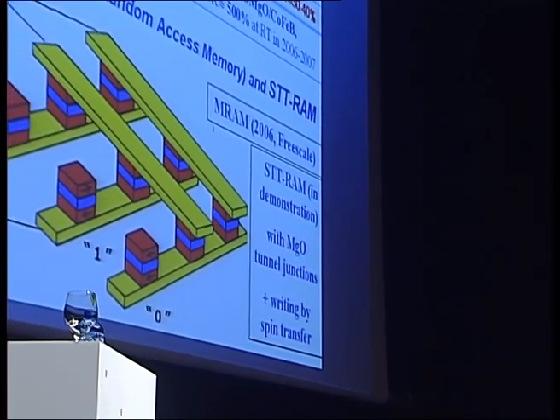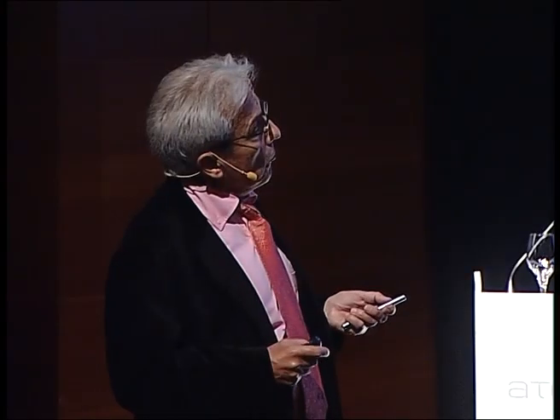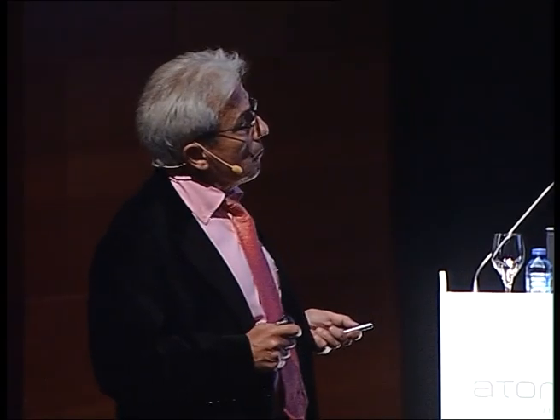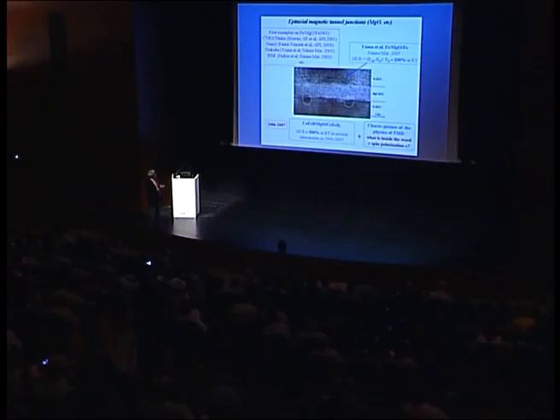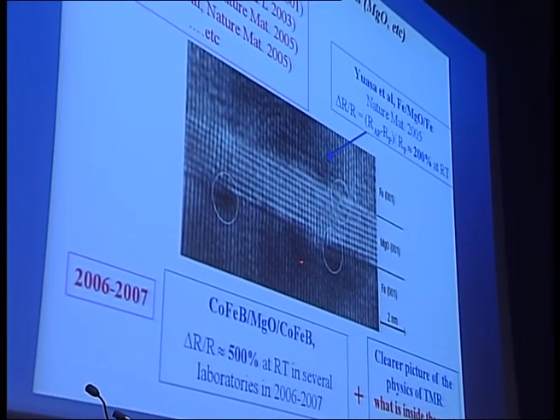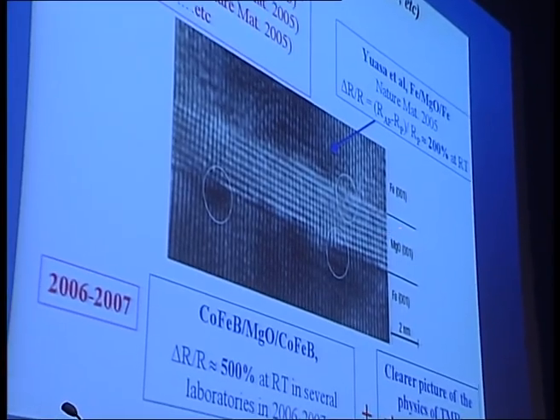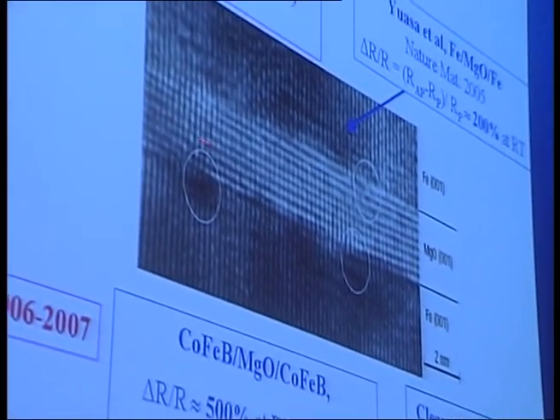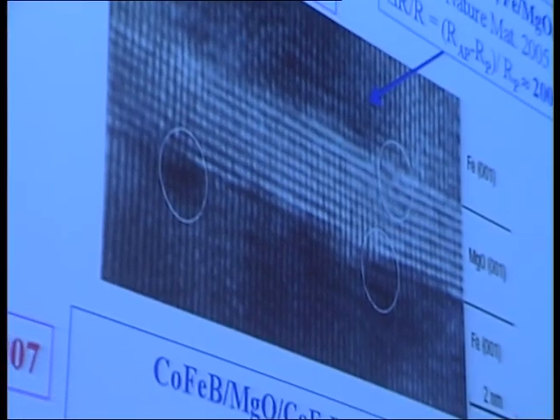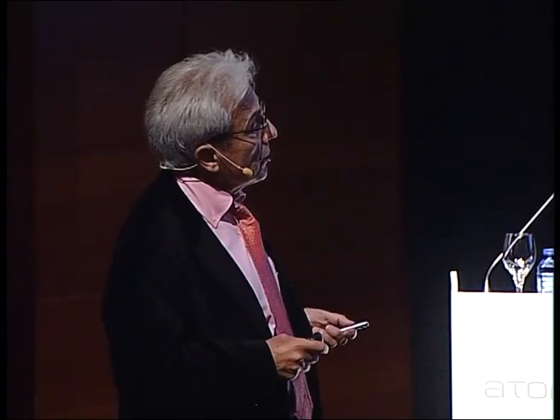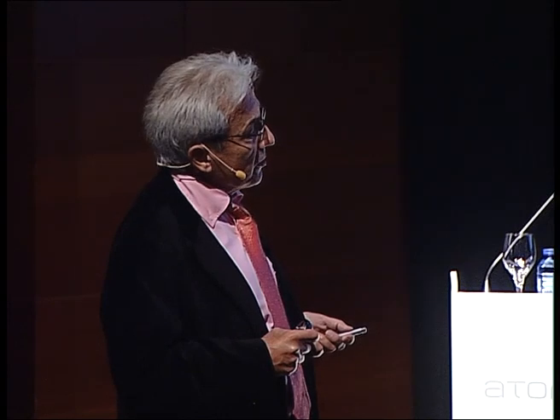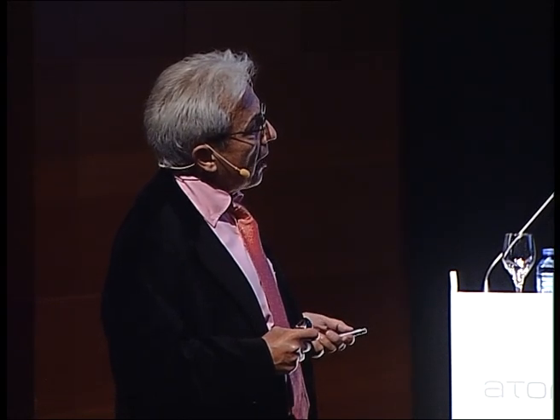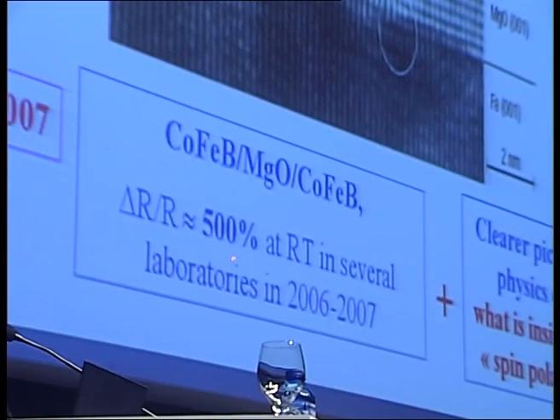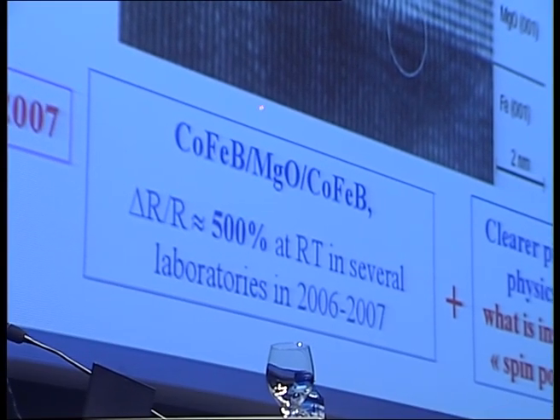First, the advance came from the transition to single crystal multilayers. So an advance in technology that allows people to prepare this type of single crystal tunnel junction. For example, you can see the atomic lines, atomic planes in MgO and in iron on both sides. And these magnetic tunnel junctions have a very large magnetoresistance ratio. 500% means that the resistivity increases from 1 to 6 when one goes from parallel to anti-parallel configuration.